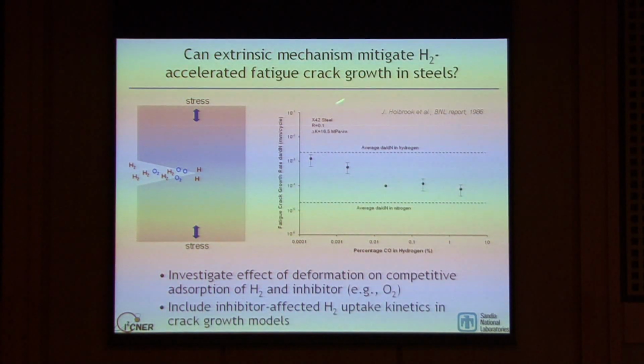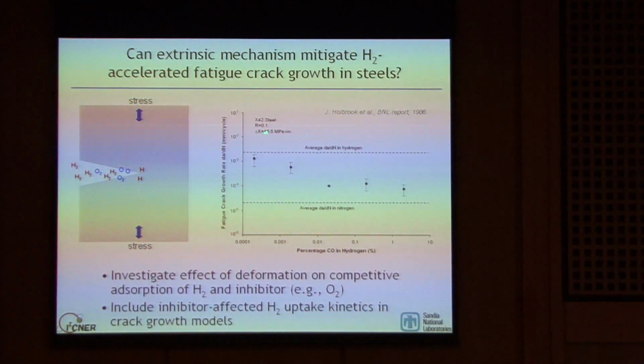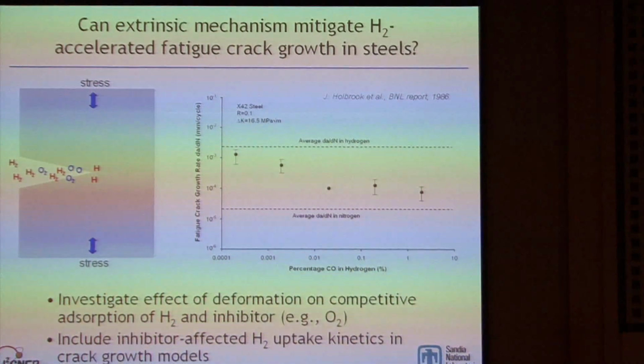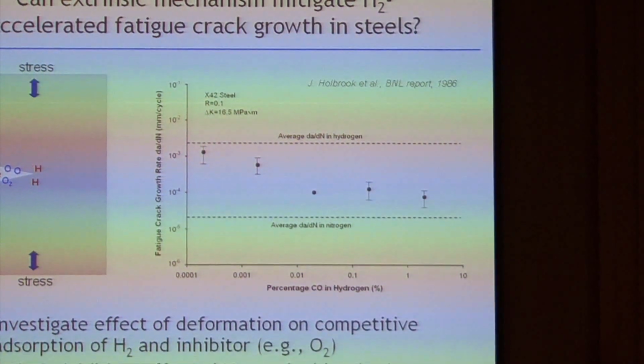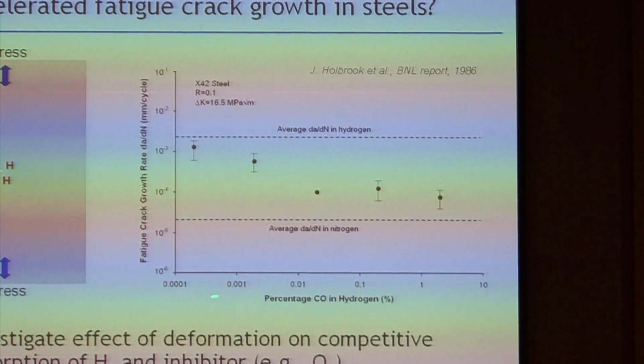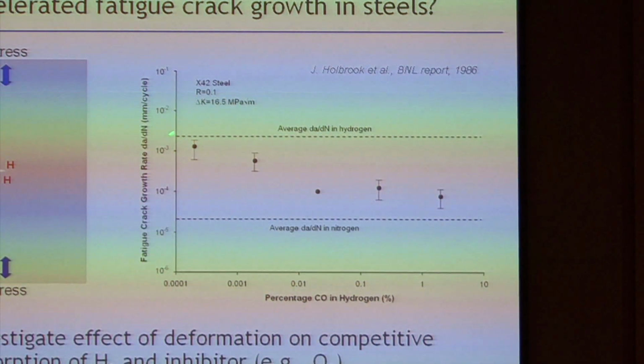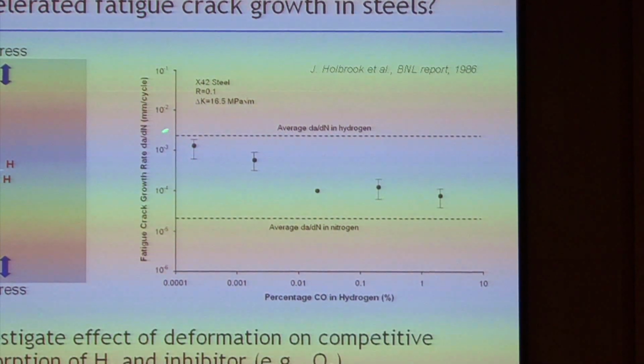I want to draw your attention first to this plot from John Holbrook when he was at Battelle Columbus in the mid-'80s. What John did was measure the fatigue crack growth rates of another pipeline steel, mixing different amounts of carbon monoxide in the hydrogen gas. This is the percentage of carbon monoxide in hydrogen. As you can see, as the percentage of carbon monoxide in hydrogen increases, the crack growth rates come down quite dramatically, to almost the same magnitude of crack growth rate as if the measurement was done in an inert gas.